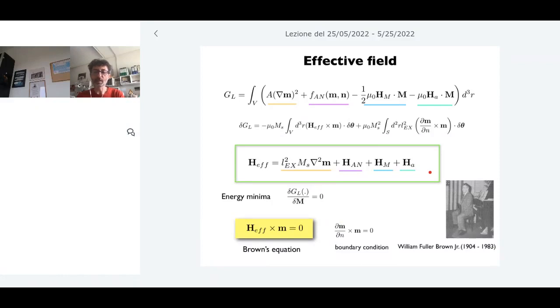The effective field is a sum. Let's start from the end. It is the sum of the applied field and the magnetostatic field. If you combine them, you have the field of Maxwell equations with magnetic material. Now, yes, they can be summed in the expression of the effective field, but not in the total energy. Then you have two extra terms that, in a quite confusing way, we call fields, but they have nothing to do with Maxwell equations.